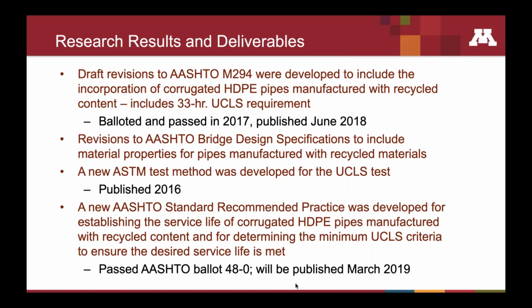In there, I do apologize, I have a slight typo. We have a 33-hour UCLS requirement. It's actually 34. There was a rounding issue on this slide, so I apologize for that. But that standard was balloted in 2017, and it was passed, and then published in June of 2018. And then we had some revisions to the bridge design specifications. That was also published in around 2018 timeframe. And then the new ASTM test method that I discussed earlier was published in 2016.